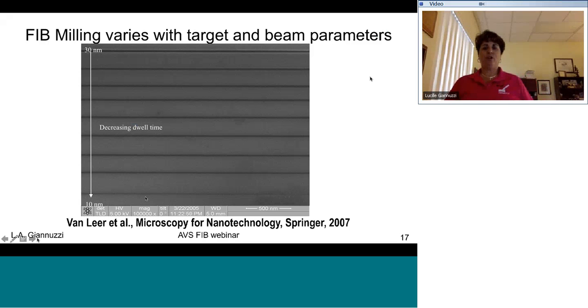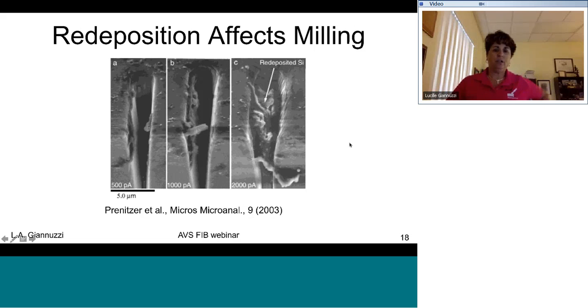The FIB milling also varies with target and beam parameters. So, for example, if you just change the dwell time, you're going to see a much wider slot, 30 nanometer spot with a larger dwell time than if you just decrease the dwell time. And this is analogous to, for example, if you're just trying to dig a hole in your backyard, you've got a shovel, you start digging a hole. At some point, you can only go so deep without whereby you can't get the material out unless you make the hole bigger. Okay, so that aspect ratio is going to be limited for a specific ion target species at a specific energy.